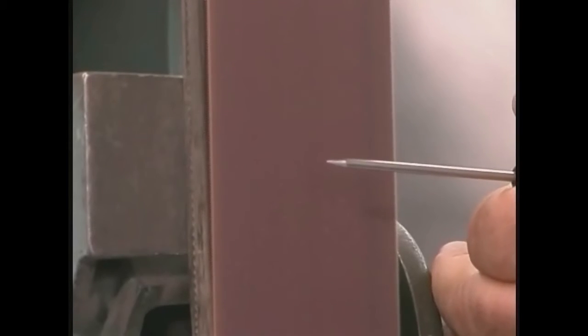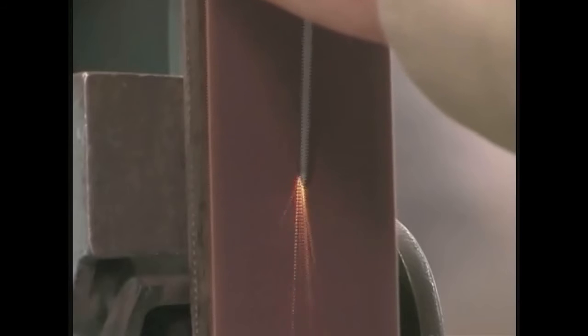I like to sand an angle on the tungsten at about the same angle that a pencil sharpener puts on a pencil. Another way to say this is that the length of the sanded area should be about 2.5 times the electrode diameter. All of the sanding or grinding scratches should go along the length of the electrode, which means that you must hold it in line with the belt or wheel as you're pointing. If the sanding scratches spiral, the arc coming off the electrode will not be as stable.